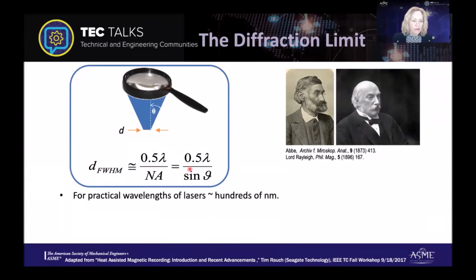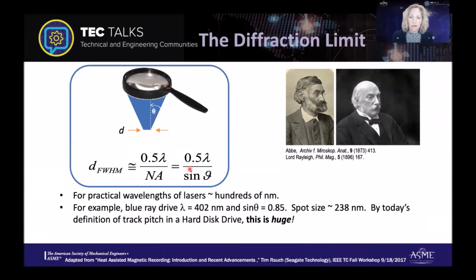And so if we think about practical wavelengths of lasers, we're still talking hundreds of nanometers. If you look at an example of one of the smallest wavelength lasers in a practical commercial sense, which is a Blu-ray drive, that's about 402 nanometers. With a practical numerical aperture, we're talking about a spot size of 238 nanometers, which is small and impressive, but with today's definition of the track pitch and the bit size, this is huge. This is much bigger than our 50 nanometer spot.